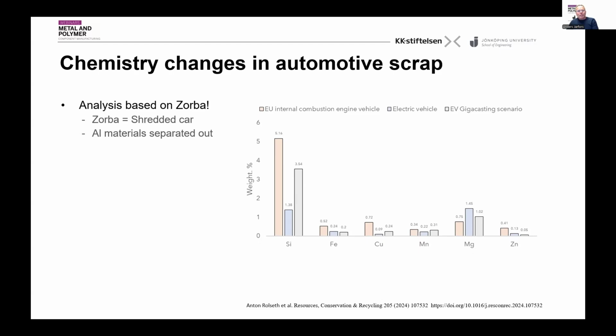The other part is that silicon is also a very dirty element when it comes to carbon footprint. So 70% of the carbon footprint in the recycling process is also coming from the silicon addition. So that means there is a need to rethink your alloying systems and maybe match what is coming out of Zorba a little bit better, even if you want to do castings. And this is what we see for mega castings, for instance, that there is a change in that. But the first thing that we need to deal with is what happens when we change to the electric vehicle.